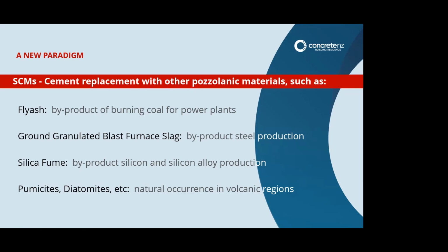And then there's also silica fume, also an industry byproduct from silicon production and silicon alloy production. For silica fume, the replacement value is about 10%, not really much more, but silica fume is more used to enhance the strength of the concrete.